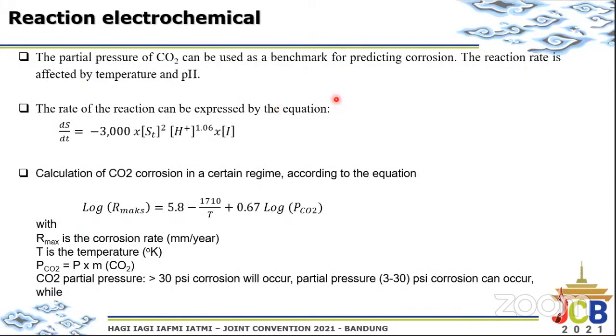This is the electrochemical reaction from the CO2. We can calculate manually, and you can also use this formula from Norsok 506, and this is for consideration. We predict the CO2 fugacity and then calculate to predict the corrosion rate in MMPY.